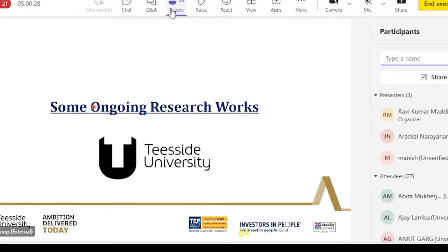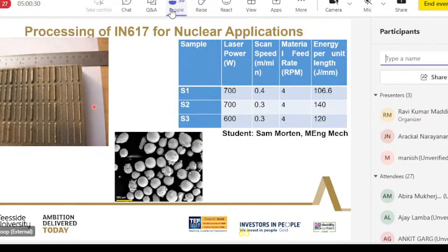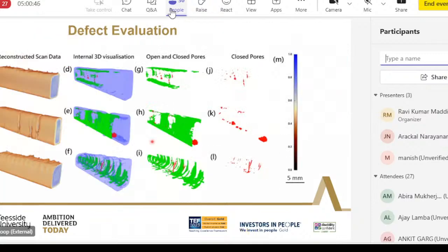Some ongoing work that we are doing at the moment is on processing of Inconel 617 for nuclear application. One of my MTech students has done this work. So we deposited Inconel 617 at three different energy densities. We made three different blocks. This is the powder that we use for that. The major finding that we could get out of this is the effect of energy density on the defect formation and the grain structure. We could see that S2 has the highest energy density, S1 has the lowest, and S3 is the middle one.